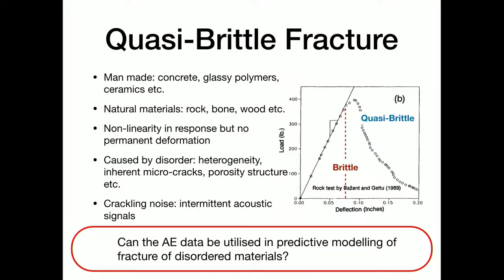What is also characteristic is that these micro cracking events result in crackling noise. It's measurable as intermittent acoustic signals. Now this is very valuable information because it's happening prior to the final event, and it would be of immense use if we can utilize this data in some sort of predictive modeling of fracture of disordered materials. So that's the broad question: can we use the AE data in predictive modeling of fracture of disordered materials?